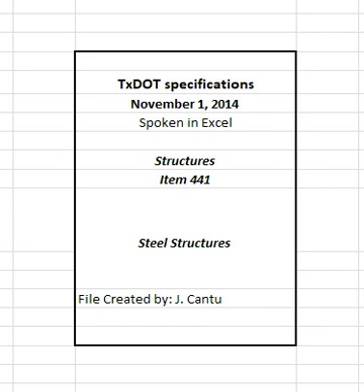Do not mark fascia surfaces. Use one of the following methods as soon as possible to remove any markings or any other foreign material that adheres to the steel during fabrication and could inhibit the formation of oxide film: SSPC SP1, Solvent cleaning; SSPC SP2, Hand tool cleaning; SSPC SP3, Power tool cleaning; and SSPC SP7, Brush-off blast cleaning. Do not use acids to remove stains or scales. Feather out touched up areas over several feet.